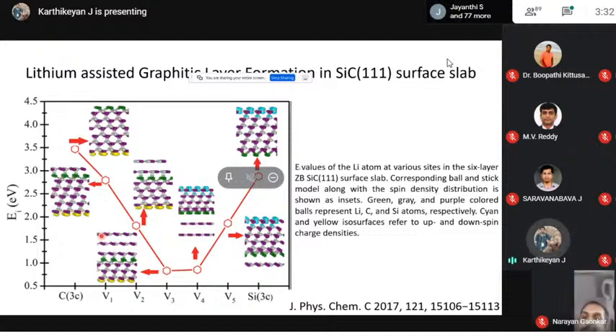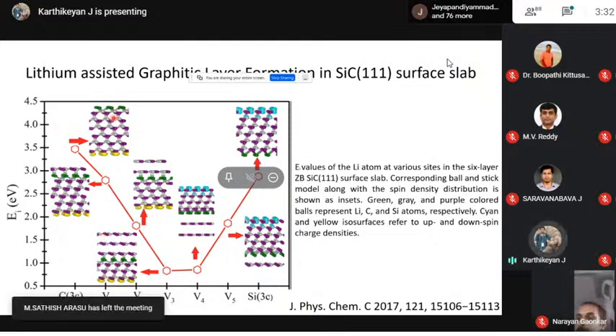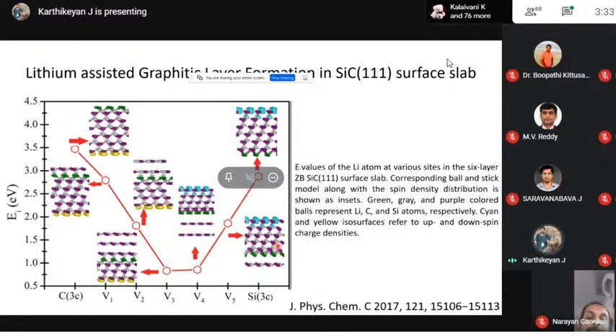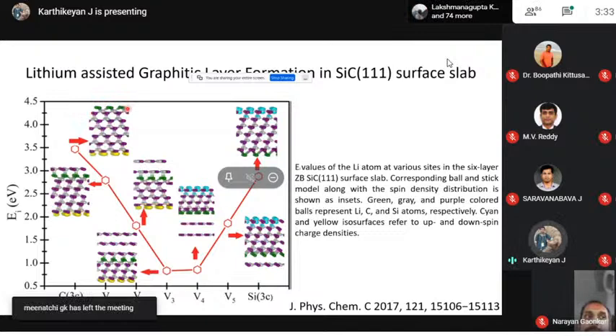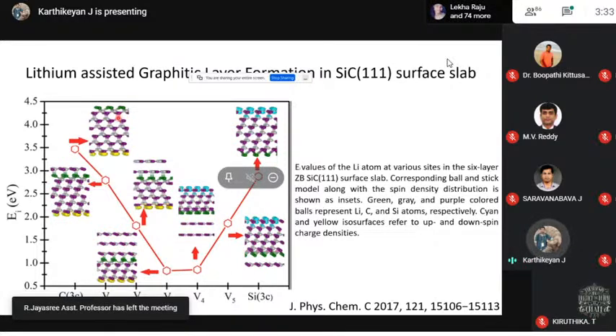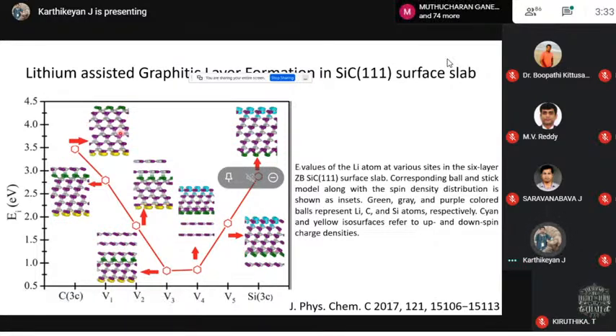So we put the lithium on different sites. One is we can put the lithium on the surfaces. This surface is a carbon terminated surface. This is 3 coordinated carbon on the surface. Here this surface is actually a silicon terminated surface. Here we have silicon in 3 coordination. So we can put the lithium on the surfaces of the carbon terminated side, or the surfaces of the silicon terminated side, or we can also put it right below the first layer of silicon carbide, or below the second layer, or below the third layer. So we can put the lithium in different sites of this surface slab, and we got the energetics.